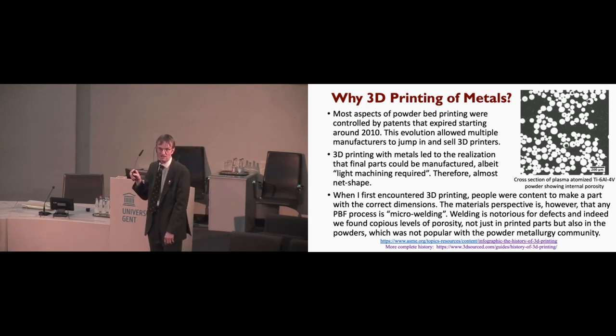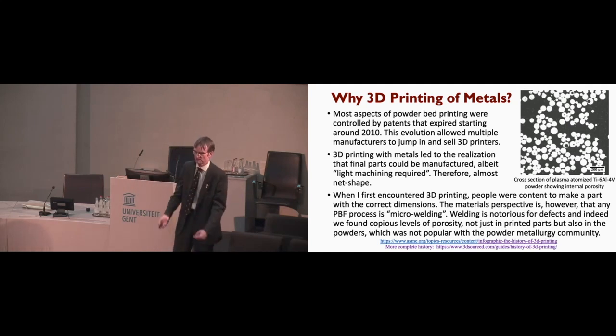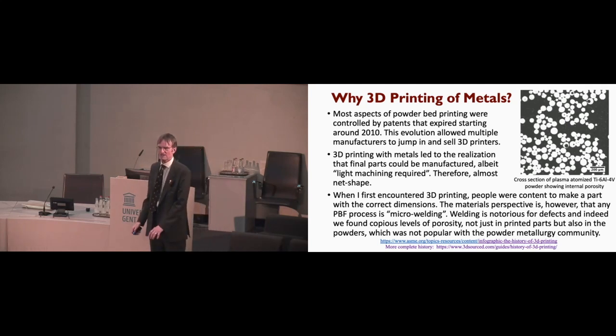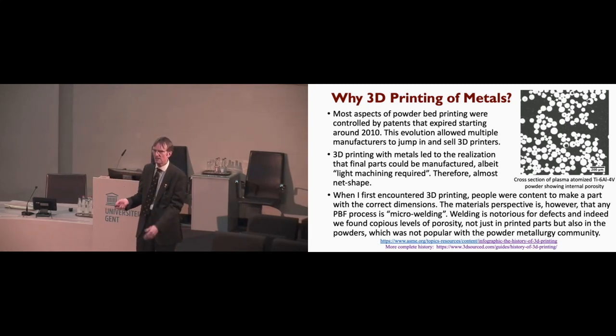And as a little anecdote, we were very unpopular in the powder metallurgy business for a little while, because they hadn't appreciated that most of their powders actually had a significant porosity fraction. The reason it hadn't been an issue was they had always cold-pressed, hot-pressed, or hipped their parts. They'd never just taken the powder and melted it and resolidified it, which allows some of this porosity to survive. So there you have something that was at least a little bit counterintuitive that we ran across pretty early on.